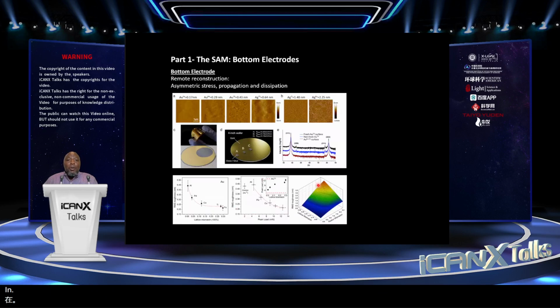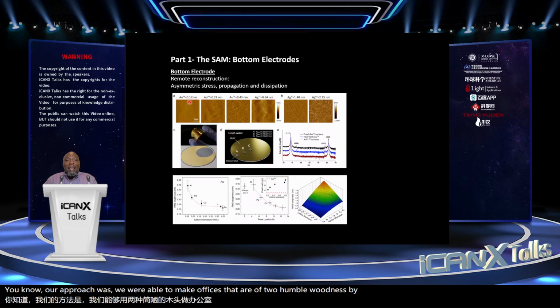And our approach was that we were able to make surfaces of tunable smoothness by adding an add layer to the gold. After we deposit a second metal on top, that allows us to introduce interfacial strain. Because we don't penetrate the gold film all the way, we only cause strain defects. Those defects propagate and reconstruct the surface without changing the faceting.